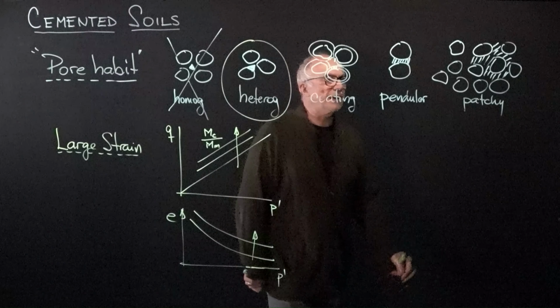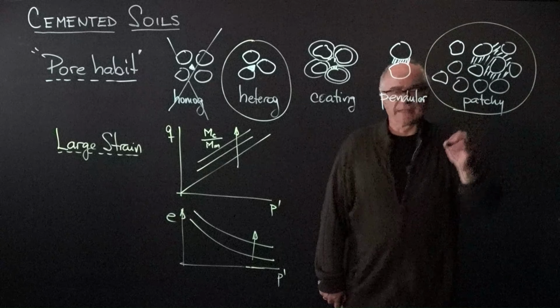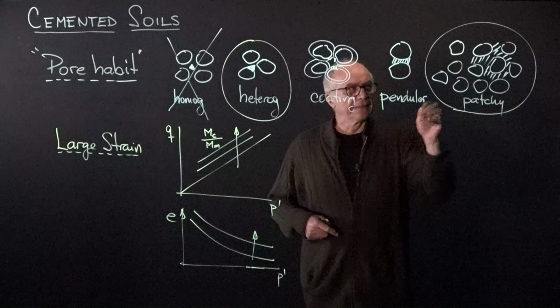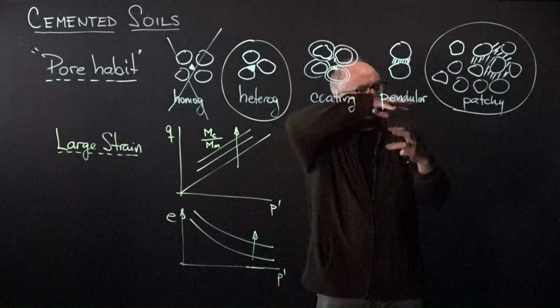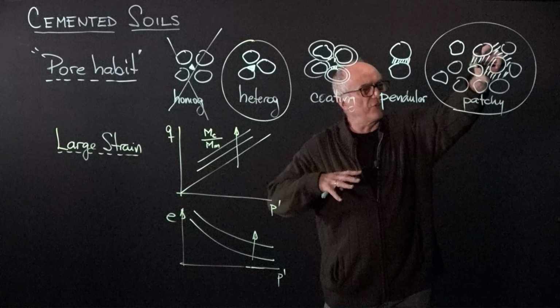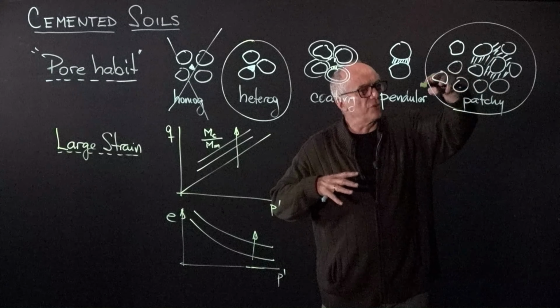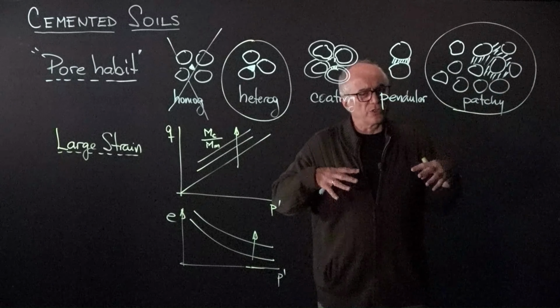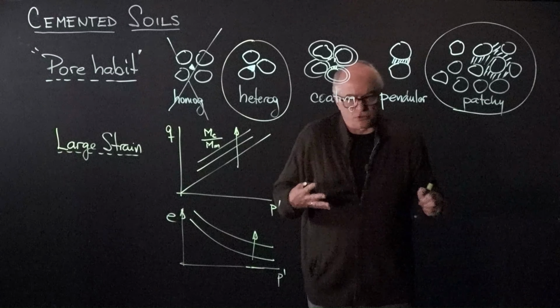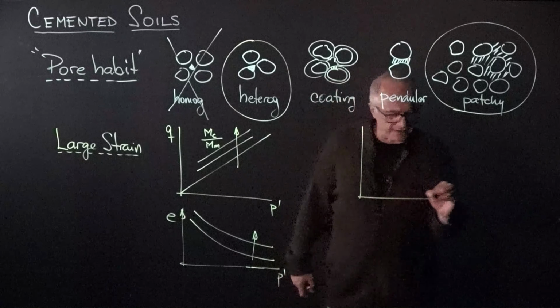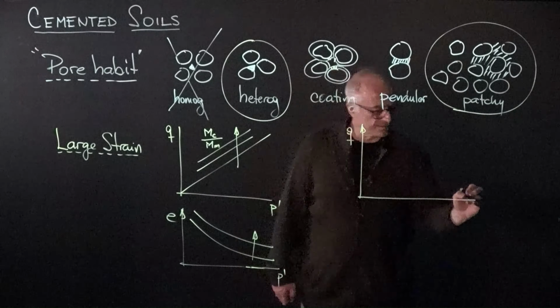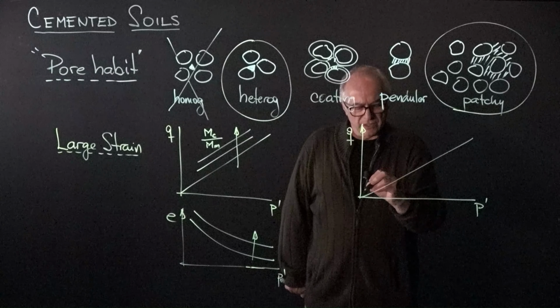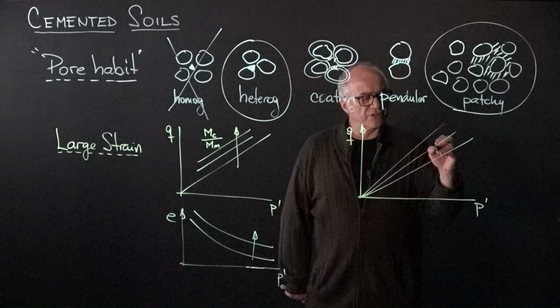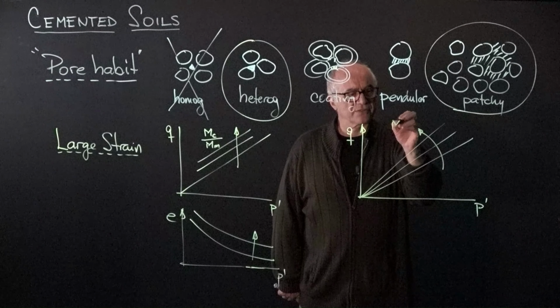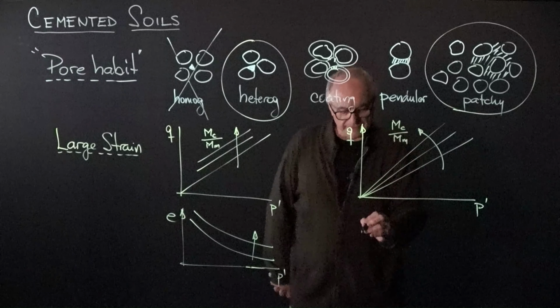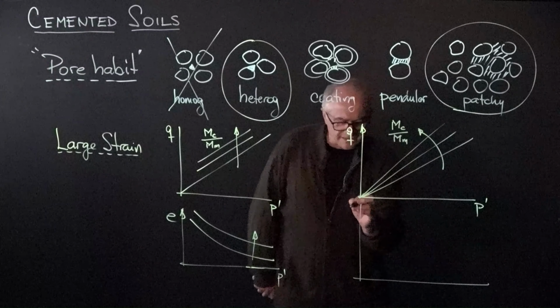Now let's explore the case for patchy saturation. And patchy saturation has a different effect. Notice that during shear, a failure plane will probably avoid the patch, which is very strong, and so the failure plane will go around the patch, which demands more energy to shear, but it's still a very frictional system. And so in the QP space, if this is the uncemented soil, we see an increase in friction angle due to the mass of cement with respect to the mass of the mineral. And the effect translates in EP prime